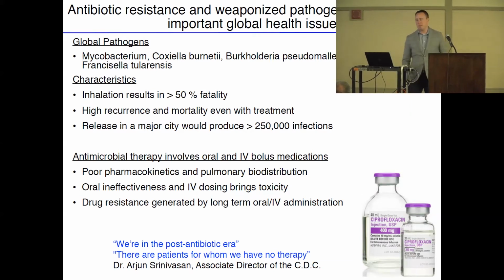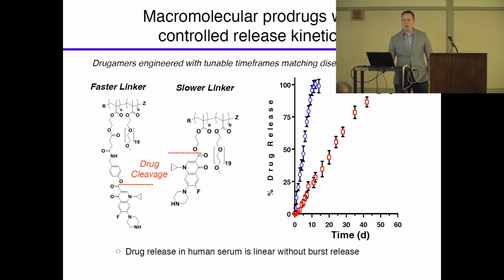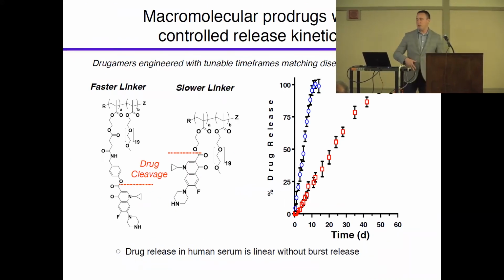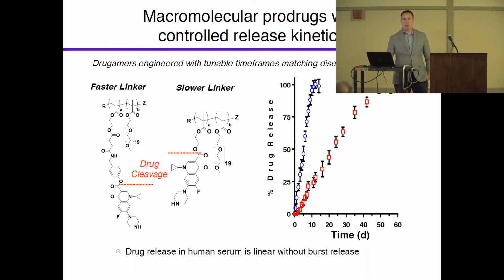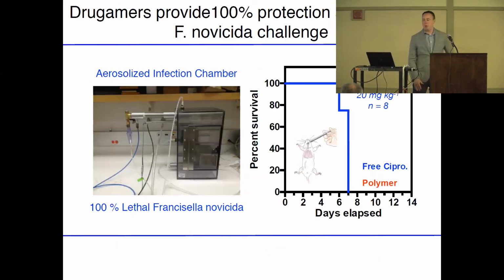Also, antibiotics are a hot area because, as the director of the CDC said, we're entering the post-antibiotic era. So, quickly, we can show we can make these things with very well-controlled zero-order release kinetics. It's very linear over anywhere from a few hours to several days. The proof is kind of in the pudding. So what we did is an aerosolized infection model, and you can see even with the free drug, this is a 100% lethal model, and almost all the animals died after 6 to 7 days, whereas we were able to recover 100% of the animals to the end of our study.